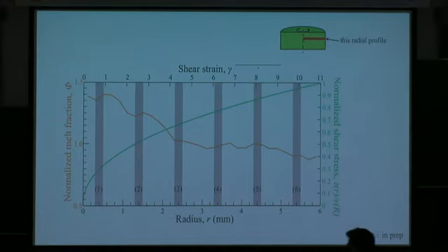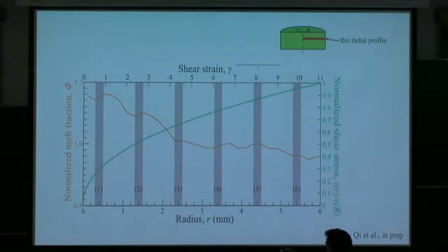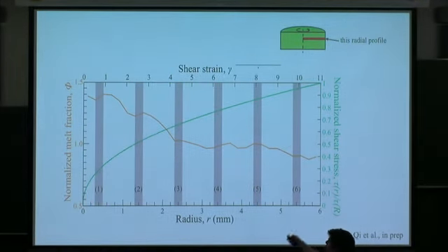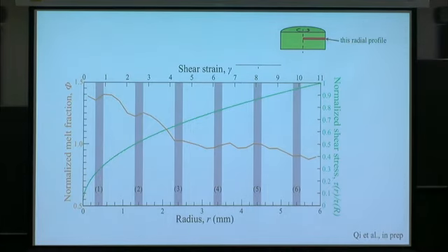First thing to look at is the melt fraction as a function of radius, which remember is also a proxy for shear strain. And we see the melt fraction is higher in the center and it dies off towards the edge. Okay, so that's our base state segregation. This green curve is showing a prediction for what the stress magnitude is as a function of radius, and it's a complicated nonlinear function, and it's difficult to approximate, so you have to make some assumptions to get that curve, but just to show you that it is complicated.